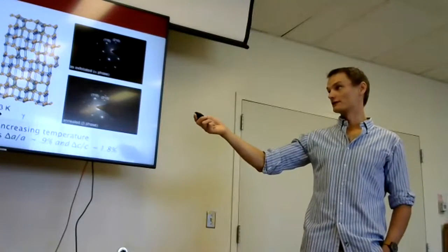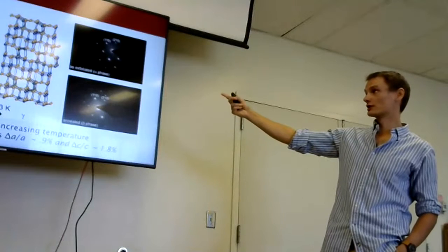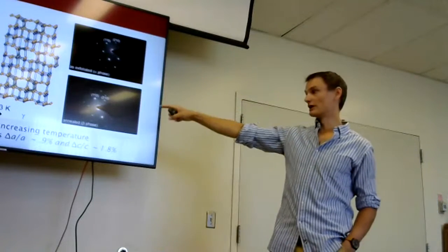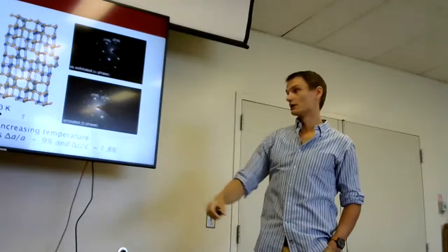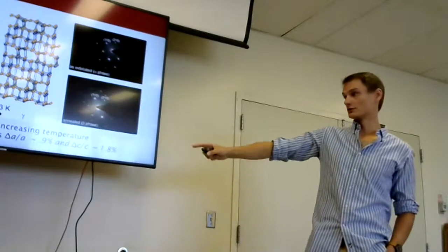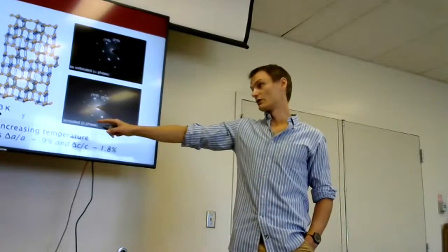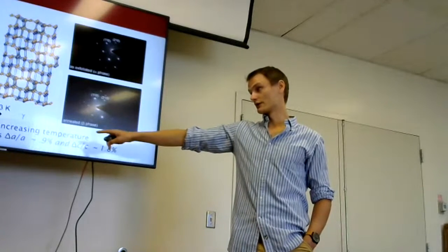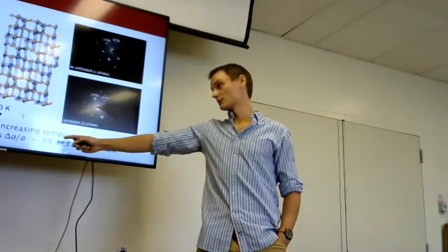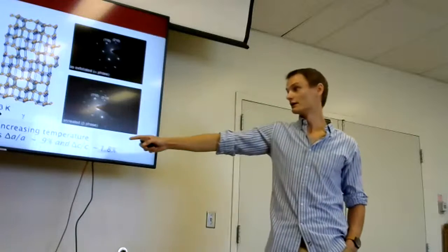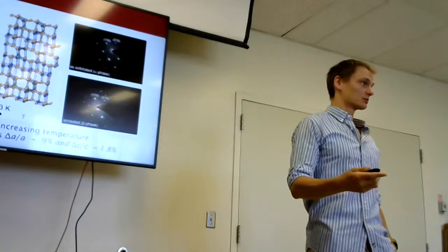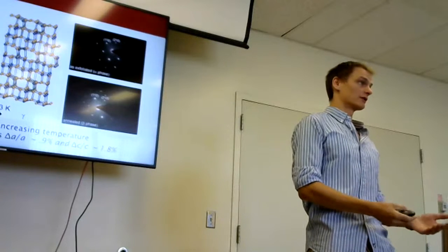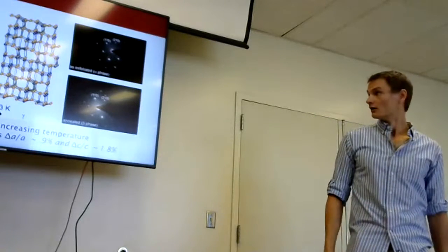So very similar crystal phases, as we can see with the TEM image here, where alpha and beta have a lot of the same symmetries. And the other thing I want to draw your attention to is that the alpha and beta phase are so similar that their in-plane crystal asymmetry in the delta A over A is less than 1%, and their out-of-plane is less than 2%, which means if you make a device, you won't have very many lattice mismatch problems.